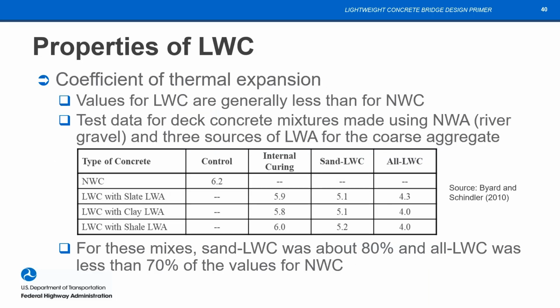Coefficient of thermal expansion is also reduced significantly. More data from the Auburn study is shown here, and that can be very important for cracking tendency, especially of decks, where they heat up when they're hydrating after pouring, but then they lock into the girders, and then when they cool off, they get a significant thermal stress and can have early age cracking. This, along with the lower modulus, can compound to give a significant reduction in cracking tendency for a lightweight deck.